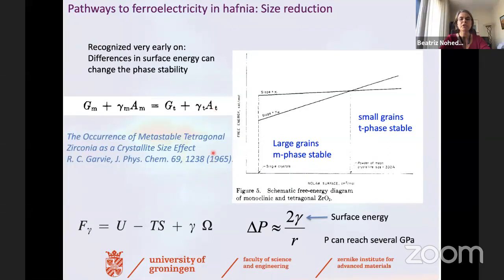And this has actually been known for a long time already, that one can go from the monoclinic phase to the tetragonal phase by reducing the size of hafnia or zirconia. So large grains will have the ground state monoclinic phase, while small grains can actually cross over to the stability of the tetragonal phase. And this is well known in nanoparticles: if you reduce the size enough to create enough surface energy, then there is a huge internal pressure induced in the middle of the particle that is inversely proportional to the size of the particle, to the radius of the particle.